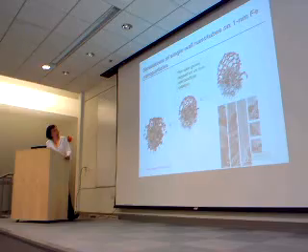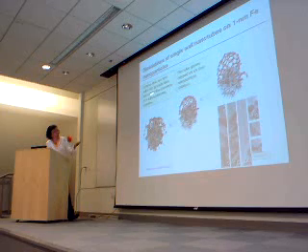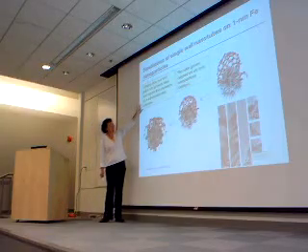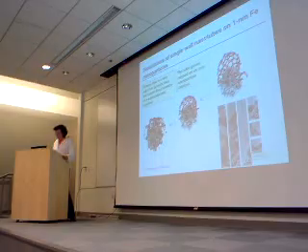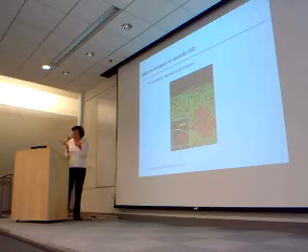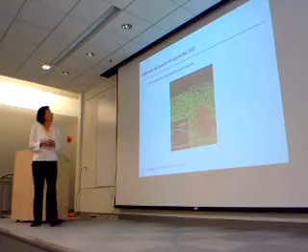And there are quite a number of things that you can understand. You can understand, for example, that your nanotube grows capped. And you can also understand that there are conditions under which your nanotube may grow without the presence of a supersaturated solution. So why is this important? Because this tells you about the experimental realization of the growth of these nanoparticles. Okay, so I hope this gives you an example of what you can do, and the fact that there are very many exciting problems that you can deal with in molecular dynamics.